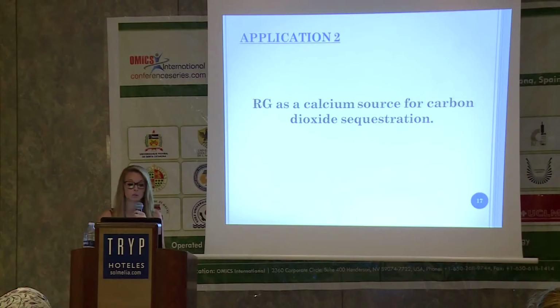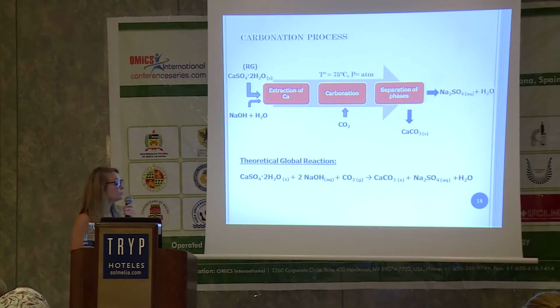In the next slide, I explain the second application with red gypsum. And in this case, red gypsum was used as a calcium source for carbon dioxide sequestration. The carbonation process involved the extraction of calcium using a sodium hydroxide solution, followed by the reaction with carbon dioxide in aqueous phase in this condition. And after, the product was separated by filtration. This is the reaction that takes place.